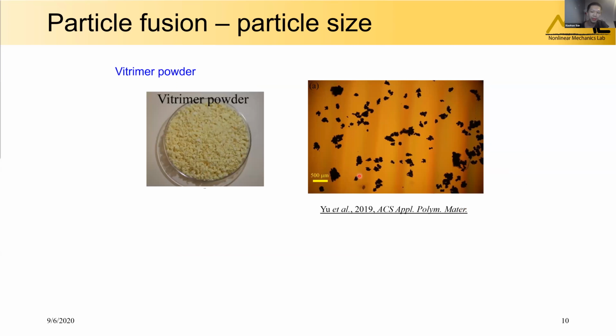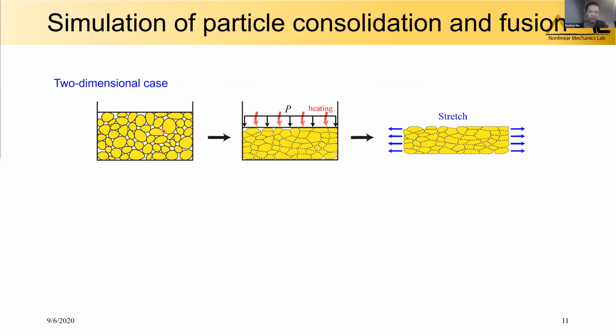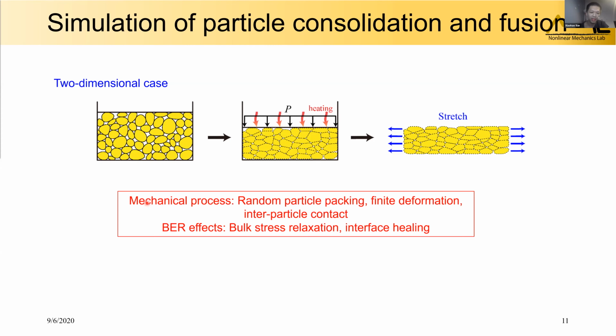Also, the Vitrimer powder shows a very random particle size. How the particle size affects the fusion process is the second question we want to answer. So we will build the finite element model for the problem, and the two-dimensional case is considered here. For the mechanical process, the random particle packing, the finite deformation, and the interparticle contact will be considered. Also, the bond exchange reaction induced stress relaxation and interface healing will be modeled.